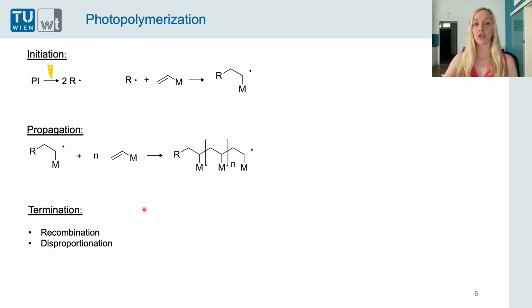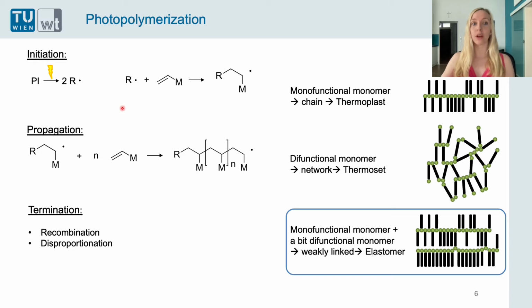And you also have termination reactions like recombination of two radicals and disproportionation. So if you have a monofunctional monomer, like in this propagation step, you get a chain if you do the photopolymerization, and therefore a thermoplast-like material. If you have a difunctional monomer, every molecule can cross-link, and you get a highly cross-linked network, and therefore a thermoset material. And if you have now a mainly monofunctional monomer and a low amount of difunctional monomer, you get a weakly linked network, and this should be like an elastomer, and this is our approach for the soft ink.